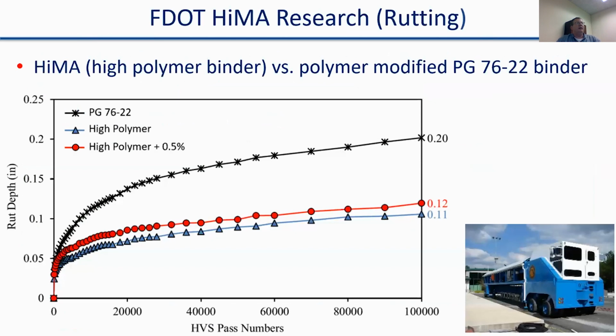Some research with respect to rutting, why we feel so comfortable. You may be familiar with our heavy vehicle simulator program here at the State Materials Office. We have 2 of the heavy vehicle simulators now, and we did some high polymer research in the past. And so we took an equivalent mix with polymer modified PG 76-22 binder and put the same mix down with high polymer and saw the rutting resistance was essentially reduced to half, again, under the accelerated loading of the HVS system there.